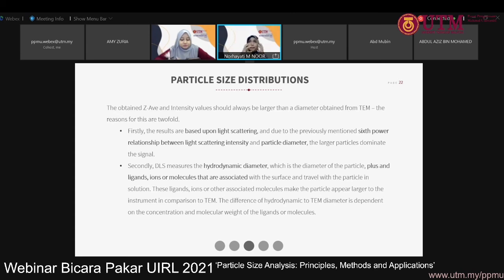Sometimes people say, my sample size for this kind of particle using DLS is 200 nanometers, but then they check with the TEM, because you can see exactly the particles, the morphology of the particles, and you get a smaller size. So what happened is, normally people have this kind of argument. They feel that their result is not correct, but there is an important point: the hydrodynamic diameter using DLS is a diameter including everything that comes together with the particles. So if your particles have an emulsifier, or some surface coating, everything comes together, compared with the TEM, which gives the pure size of the particles.